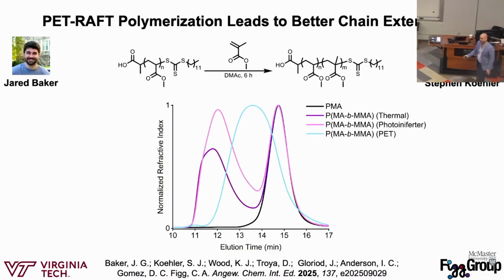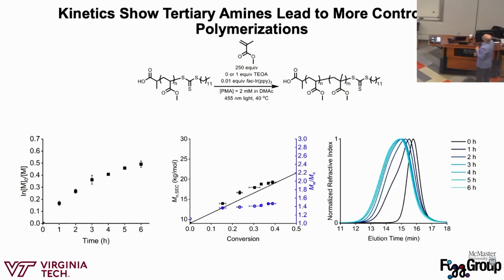Sure, it's broad. I just told you that it's kinetically and thermodynamically difficult to do this, so we're expecting it to be broad. But it is one of the first times that we can actually show that we can predictably control this shift and overcome that thermodynamic and kinetic limitation by going through a different mechanism. So we're essentially just going through the PET to activate, and we can actually extend our methyl acrylate with methyl methacrylate.